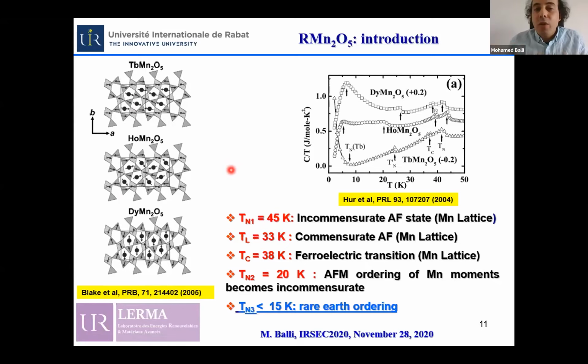Consequently, in this family of compounds, the overall magnetization is contributed by the rare earth element. Consequently, the magnetocaloric effect is also directly contributed by the ordering of the rare earth element's magnetic moment.